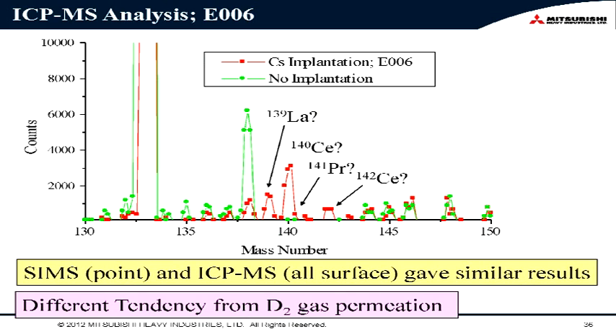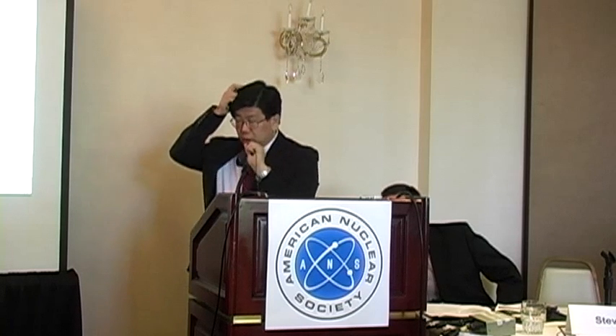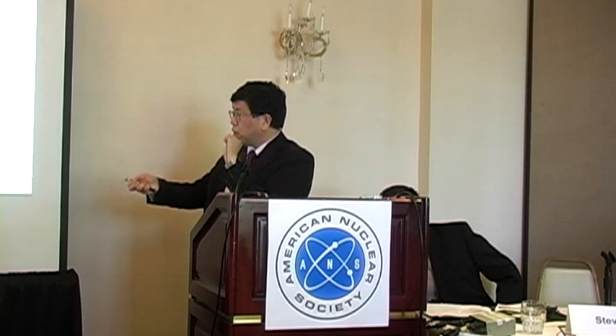Okay. And this is an enlarged spectrum around 140. We have mass numbers 139, 140, 141, and 142. A very similar result. So we can see that SIMS, the point analysis, and ICP-MS, the surface analysis, gave similar results. And also we noticed that in the case of the D2 gas experiment, we only have praseodymium, but in this case we have another mass number. So it is a different tendency from D2 gas permeation. Now we are trying this method.